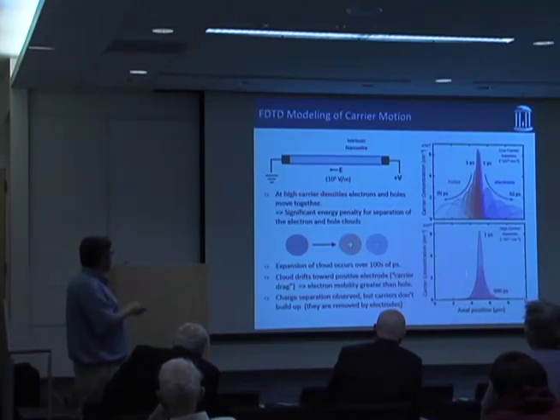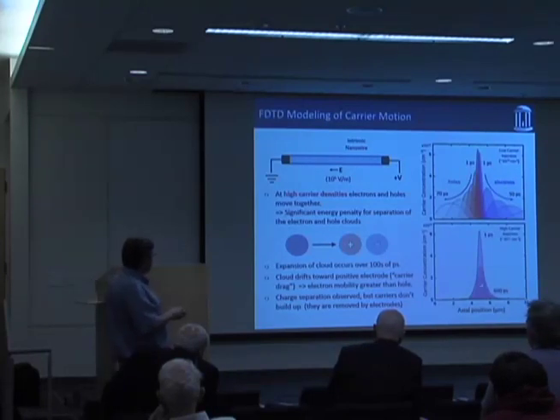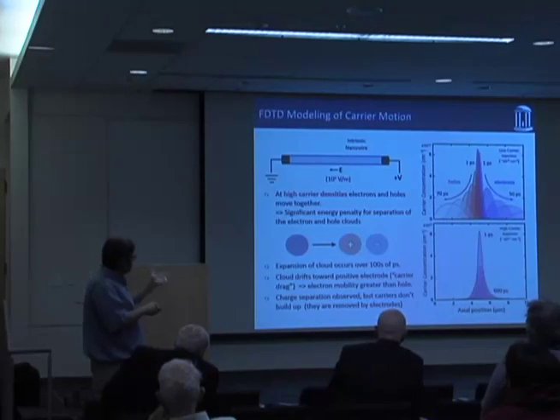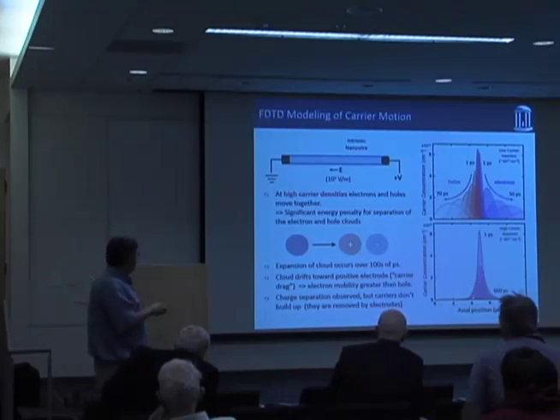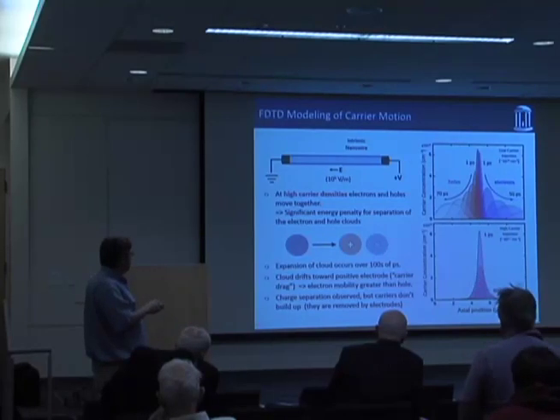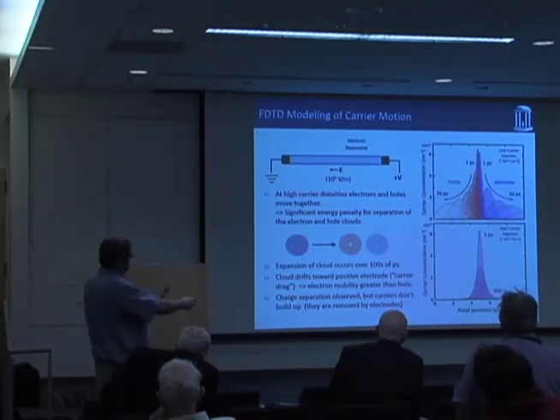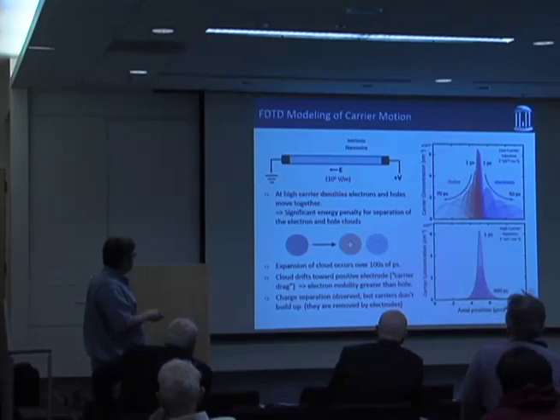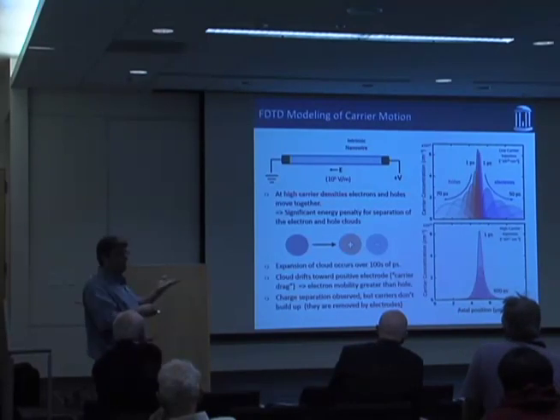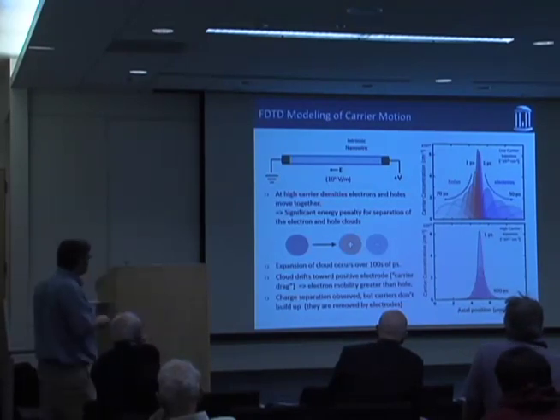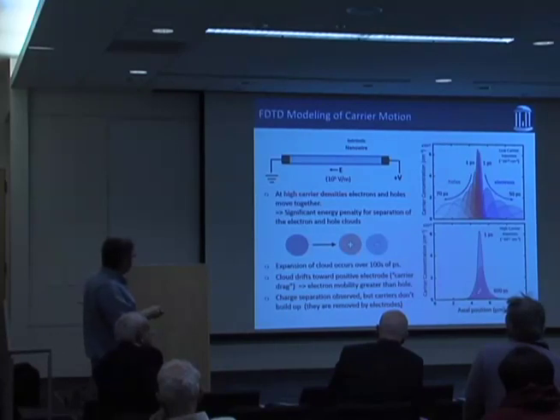So this purple shading is because the blue and the red sort of overlap. And so the electron distribution, the hole distribution in this image, or a series of images, are the same spatially along the wire. And you see a slight sort of shift of that packet towards the positive electrode, which in this case, in our experiment, would correspond with sort of the N-type region. It turns out that that shift is due to the differences in the mobilities between the electrons and the holes.